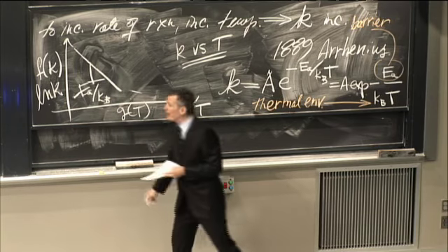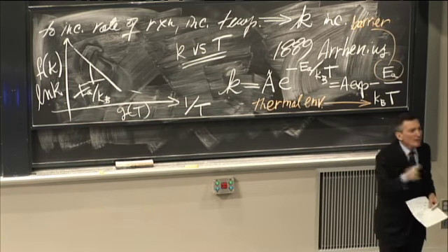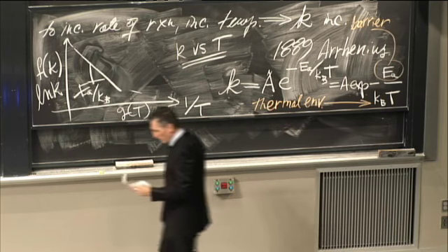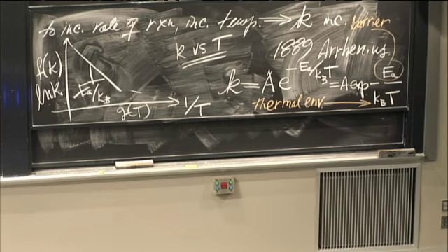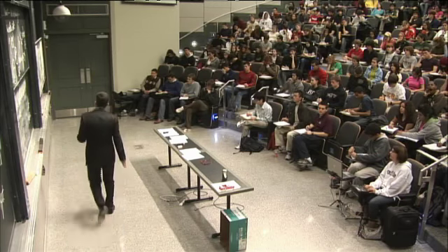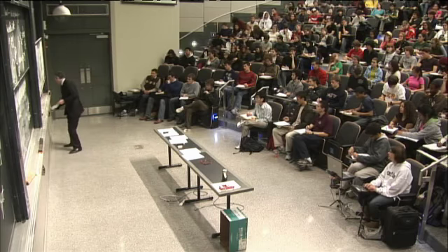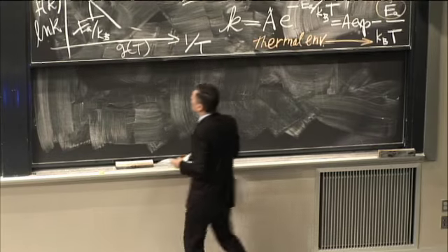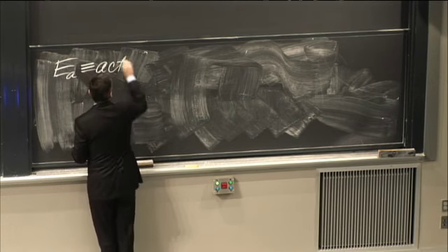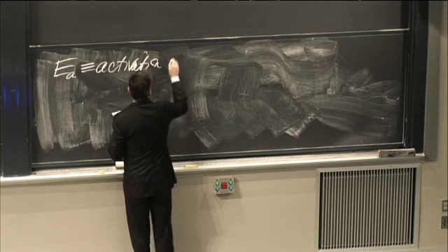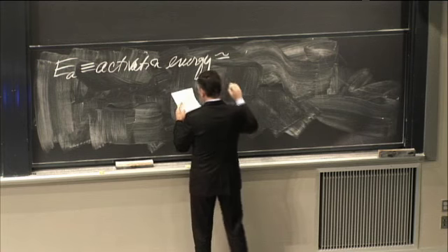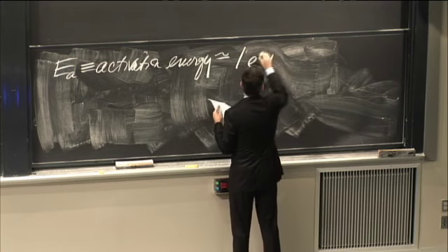So now it's linearized, and within an instant, anybody in this room can look at it and say the data conform, or they don't. So now let's think about this. What's the value of this barrier? This barrier energy is called activation energy. EA is called the activation energy. And it varies, but just to give you a sense, it has values of about 1 electron volt.